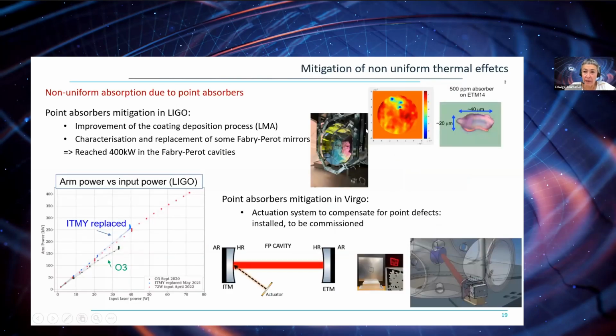The second thermal effect, as I said, is the non-uniform thermal effect due to these point absorbers. A long study has been done in order to understand and characterize those point absorbers, and it turns out that some of them were due to some kind of aluminum particles which are embedded in the coating, which is deposited on the surface of those mirrors to obtain the reflectivity. A long improvement of the coating deposition process took place in the LMA laboratory, which is coating all the gravitational wave interferometer mirrors.